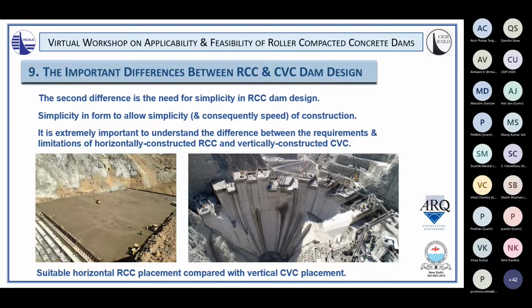Now, if we look on the right side, we see a conventional concrete construction, and in the middle blocks, you can see that there are outlet pipes being added. And those outlet pipes, yes, they slow the construction down in that particular block locally, but with the adjacent blocks being able to continue at full speed unaffected. And once the pipes are installed and finished, those central blocks can be quickly brought up to a similar level to all the adjacent blocks. So the inclusion of items or pipework, etc., through the dam in the case of conventional concrete doesn't have much real effect on the achievable construction pace.